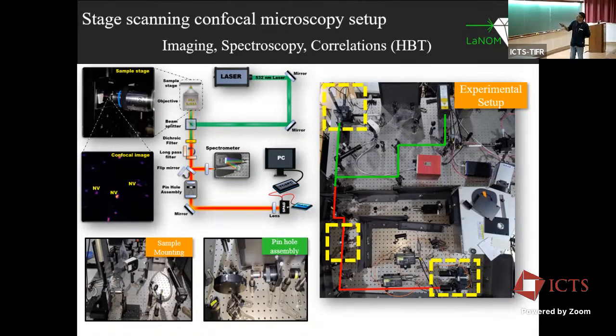And as shown here, this is a typical confocal map we get in our lab. You can see that a lot of nice NVs are placed on the substrate at different locations. And this is the actual picture of the lab. So you have a camera to image the sample. Then you can do PL measurements by using a flip mirror, and you have an HBT, Hanbury Brown-Twiss experiment, to do a single photon measurement, a single photon test experiment, which we have successfully done.